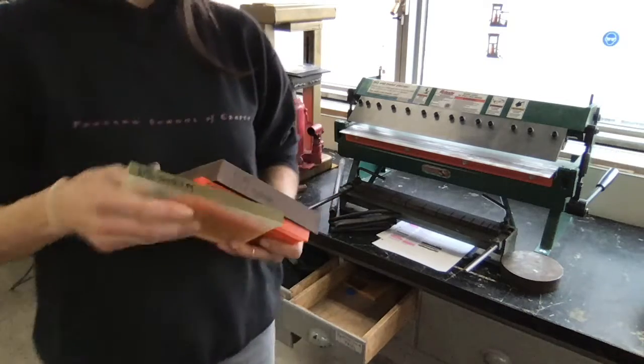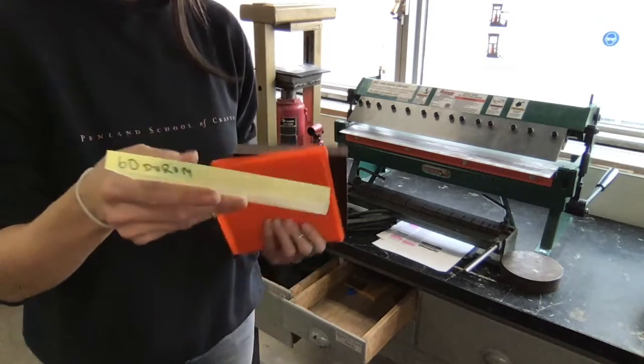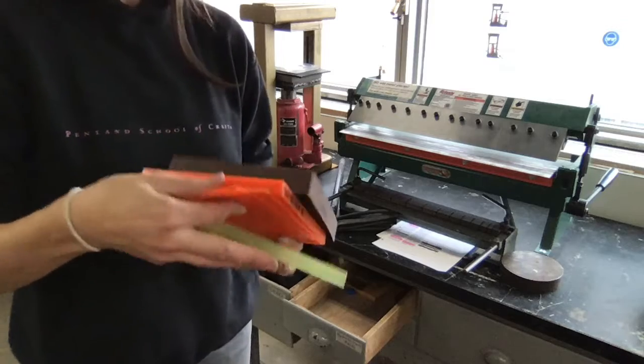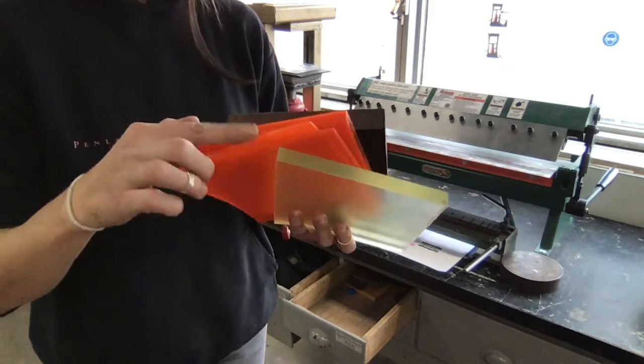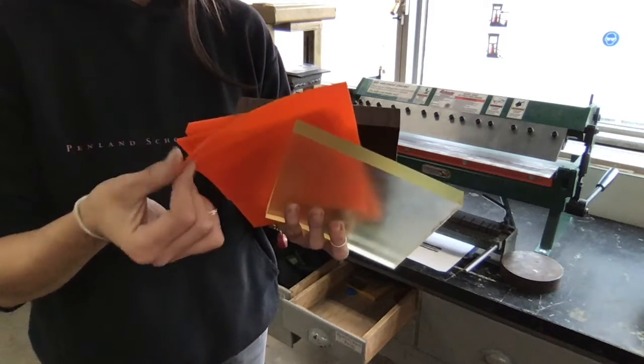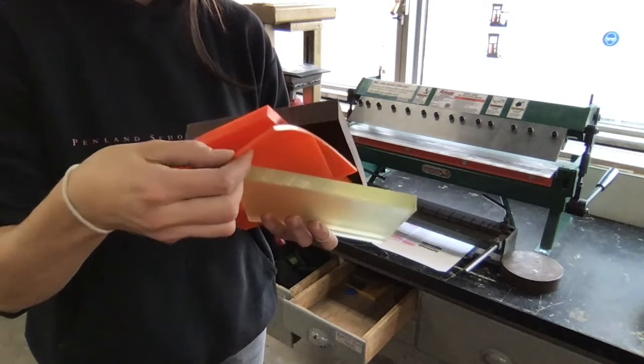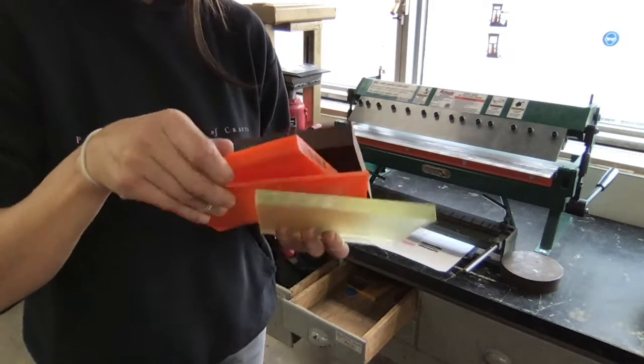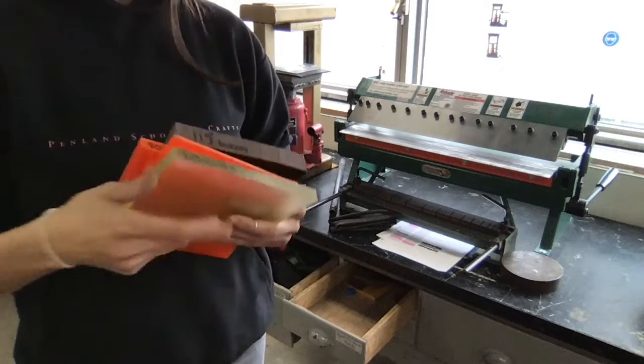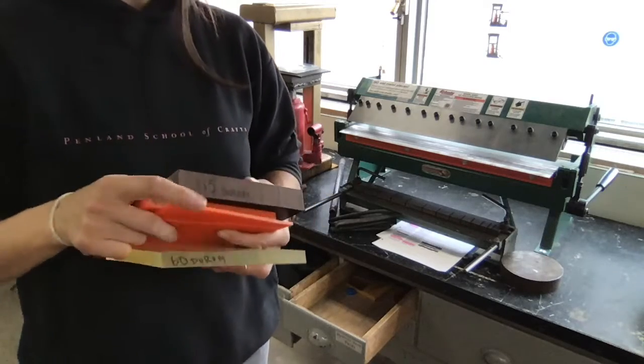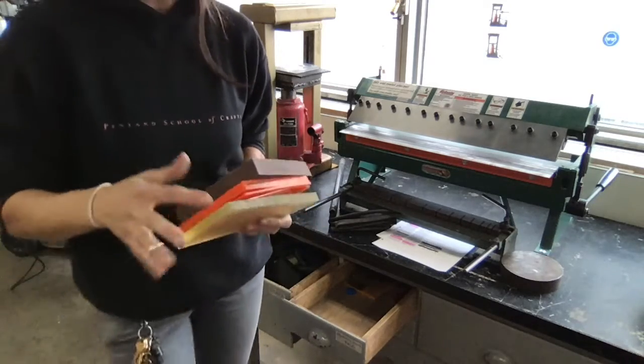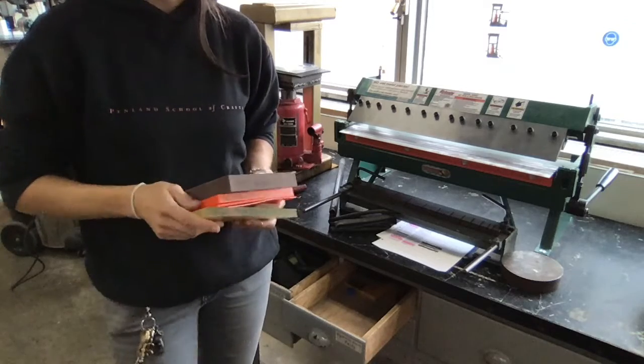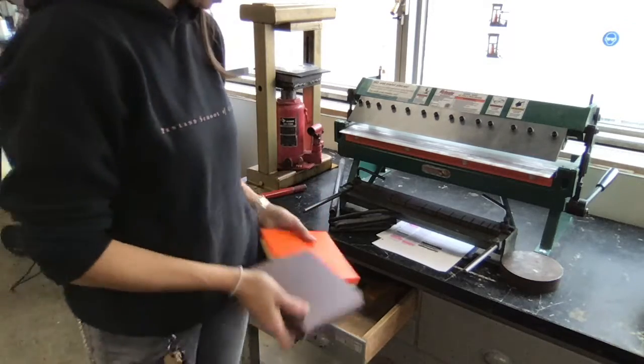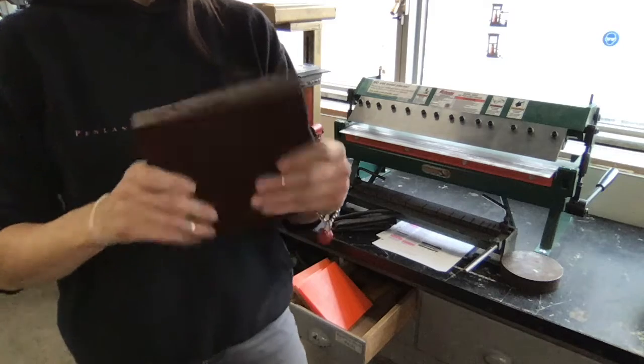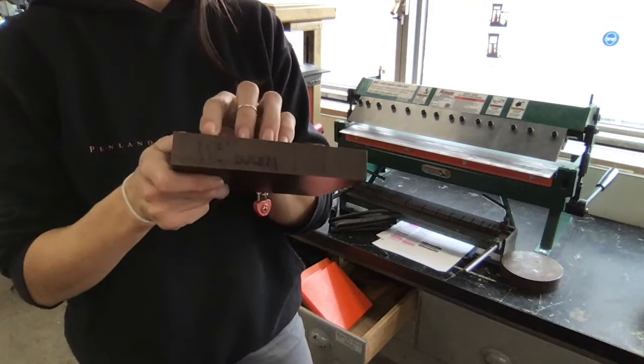We first have a 60 durometer of urethane. We have then these three 80s. So it's a 1/16 of an inch 80 durometer, a 1/8 inch 80 durometer, and then a 1/2 inch 80 durometer. 60 is the softest, and then 80 is a little bit harder. 80 to 95 is pretty standard. That's what is traditionally used exclusively in die forming. I also have a 115 durometer urethane.